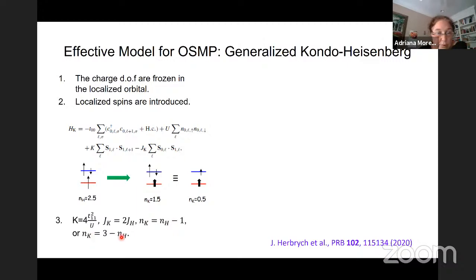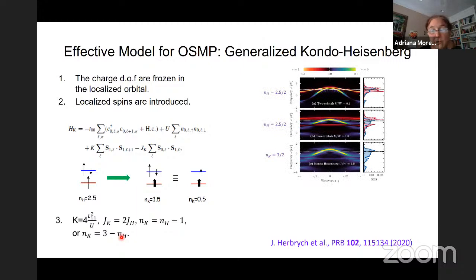In order to show you how well this model works, here are A of k omega calculations that we made. This is with the two-orbital model in the region where the Kondo model is not a good approximation, because here the two orbitals are metallic. So you see the Fermi energy here, and here is the density of states. Both orbitals are metallic. But then we go from U over W equal 0.1 to U over W equal 1.